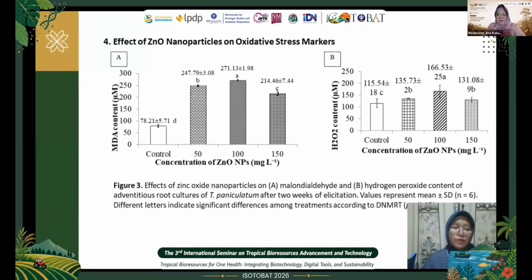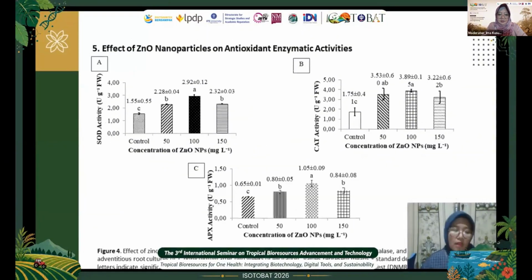As shown in Figure 3, oxidative stress markers increased substantially in response to zinc oxide nanoparticle treatment compared with control. All three enzymes exhibit a marked response to ZnO nanoparticle treatment compared with the control. The effect of zinc oxide nanoparticles on antioxidant enzymatic activity: zinc oxide nanoparticle elicitation significantly affected the activities of the antioxidant enzymes superoxide dismutase, catalase, and ascorbate peroxidase in adventitious root